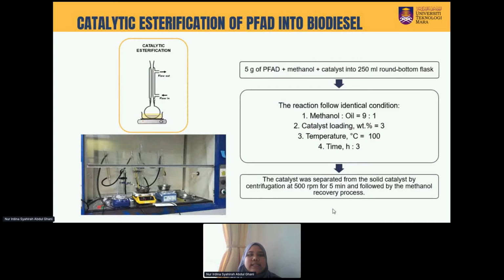So for the catalytic esterification of PFAD into biodiesel, in this study, I was only doing the catalyst screening. So this is how it looks. For the esterification reaction, I am using identical conditions based on previous studies for PFAD, which include the methanol to oil ratio, catalyst loading, temperature, and time.